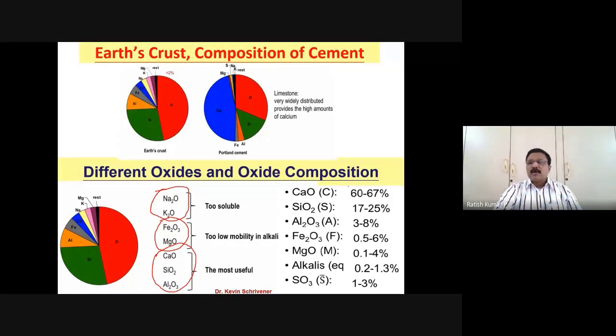And that is actually occupying, and from that you can see calcium oxide is occupying 60 to 67%, silicon dioxide is something like 17 to 25%, and alumina is occupying 3 to 8%. That is the same three materials that I'm showing here.